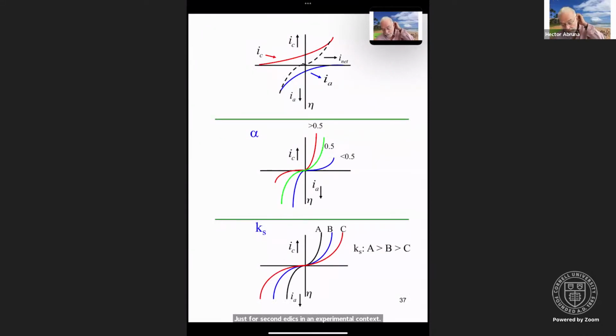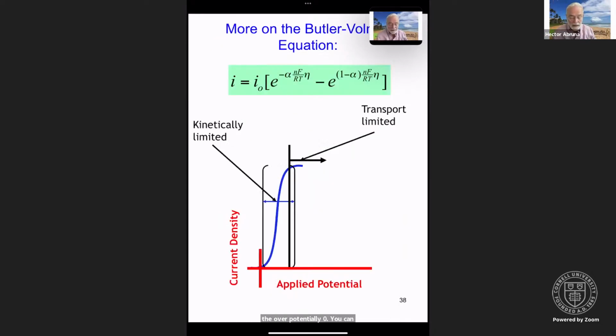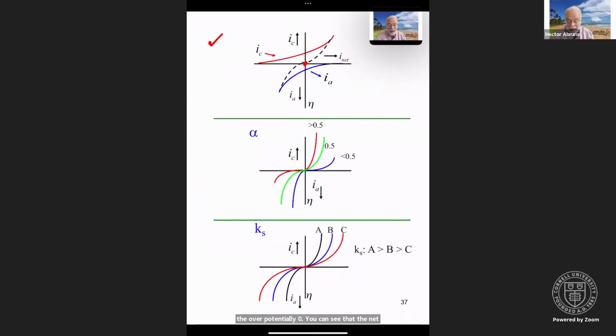And so we can draw what the individual components are and the net current. So in the top panel here, you can have the cathodic and the anodic. When the overpotential is zero, you can see that the net current is zero as it has to be. If we go to more negative polarizations, the reductive or cathodic current increases, the oxidative or anodic current goes down. At very negative polarizations, the current is dominated by the reduction. At very positive polarizations, the current is dominated by the oxidative or anodic process. And that should come as no surprise. You also see that at zero overpotential, this magnitude and this magnitude are equal and opposite, as they have to be, so that the net current is zero.